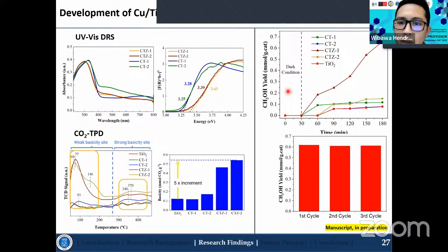Okay, so in these cases, we can see that the methanol is generated here, where we have the CTZ1, where CTZ1 is the oxide one. So based on these cases, the copper in the oxide form is very beneficial for the CO2 reductions. And the cycling is also very stable, around 0.6 millimole per gram catalyst in these cases.